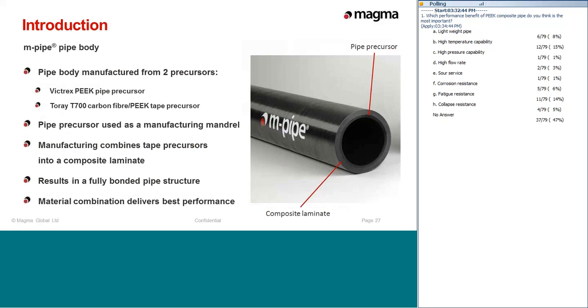We believe that PEEK offers the best performance available across a range of polymers, as Jeff has already pointed out. And in selecting our fiber, we chose Toray T700 because we believe that offers the best characteristics for the requirements of a TCP, thermoplastic composite pipe. As Jeff has already touched on, it's not only the high performance of these two individual materials themselves that deliver the performance of M-pipe, but it's the combination of them, the selection and combination of these two materials, and the good quality match between the two materials that actually adds synergy to that combination and gives us an enhanced performance, which we believe sets M-pipe as best in class in its field.